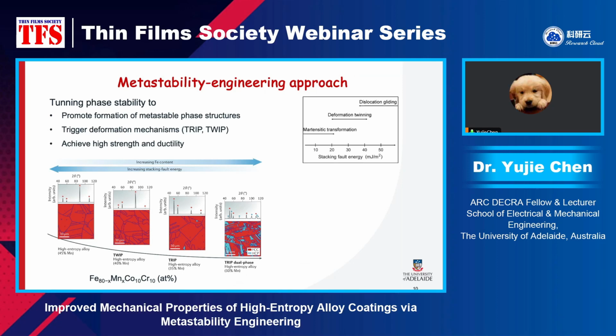So the idea here is to reduce the stability of the FCC phase by reducing the manganese content. The red color here is the FCC phase, and the blue color here is the HCP phase. As we can see, if we reduce the manganese content, we're reducing the stacking fault energy. Because manganese is the FCC stabilizer, less manganese means the FCC phase is not stable anymore, it's metastable. It starts to form the HCP phase. So that is the idea of metastability engineering. In doing so, we can form this dual phase structure, both FCC and HCP.